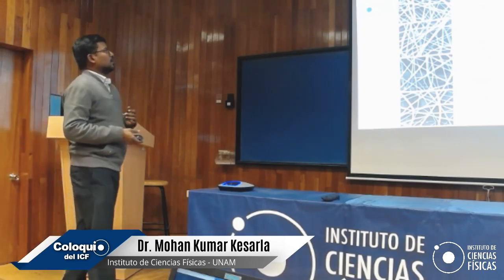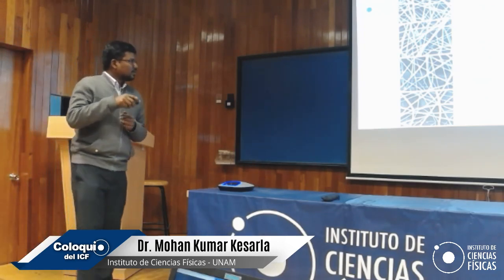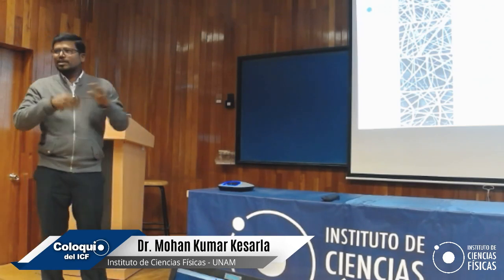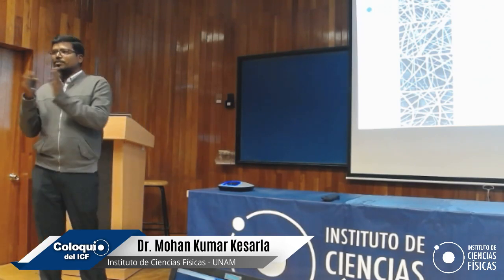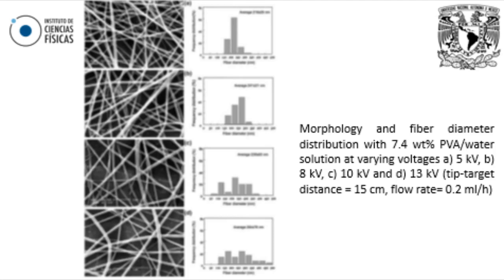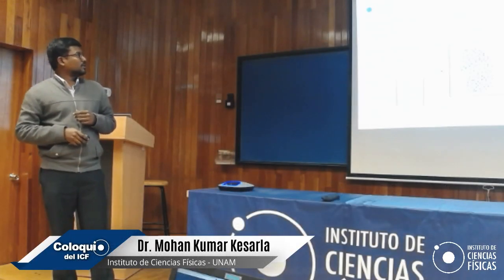And then if you play with some parametric controls like the electric field you apply for the polymers, the polymeric size doesn't change that much, but a real change is observed by a few researchers actually. There are a few different parameters we want to control well, like flow rate, distance between the tip and collector, and the collectors. The collectors must be conductive, and then the ambient parameters like humidity, and we should always see how much moisture is inside the electrospinning chamber.